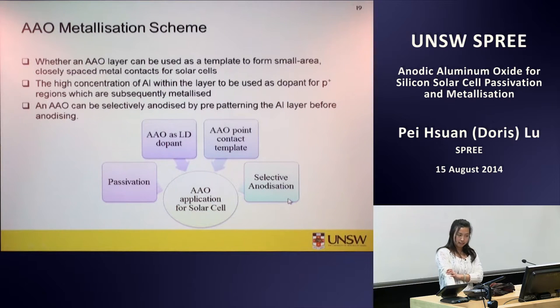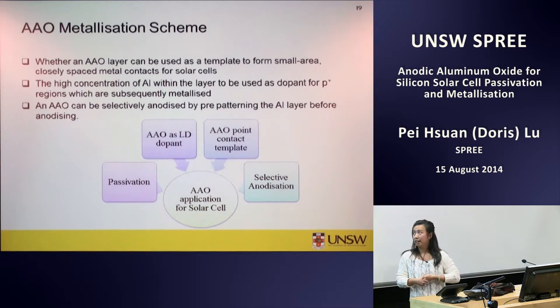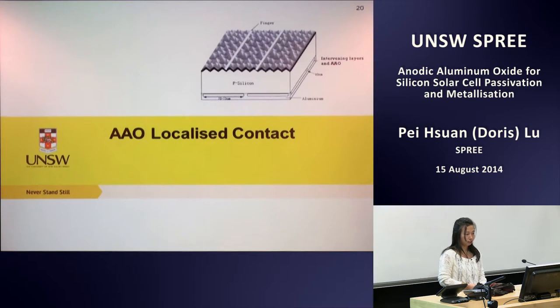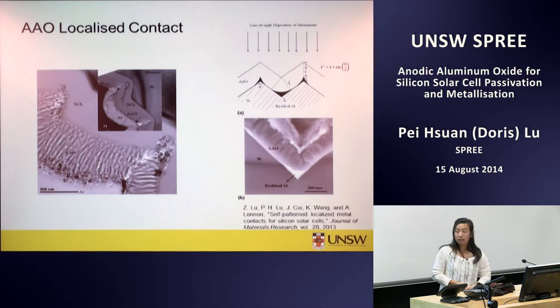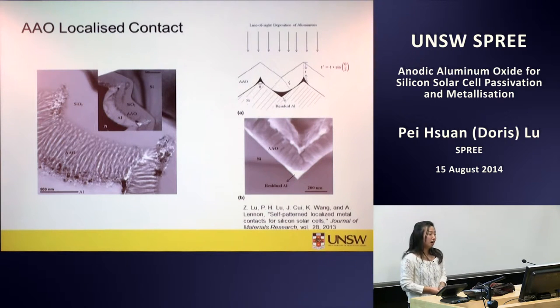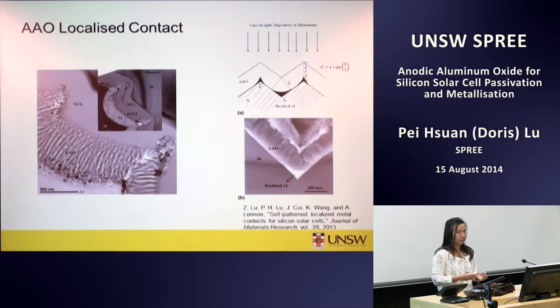So we're going to look at firstly the AAO point contact scheme, and then laser doping through anodic aluminium oxide, then finally selective anodization. This TEM image shows aluminium at the peak or valley of the pyramid. Aluminium can penetrate into silicon dioxide by firing at 800 degrees in a belt furnace. Although it hasn't touched the silicon, however, this is the first TEM image to drive this area to go forward.